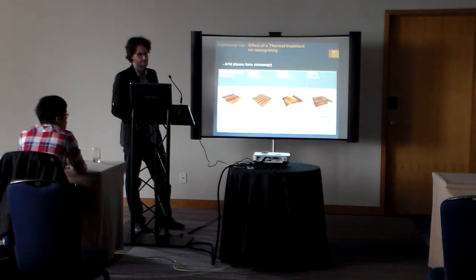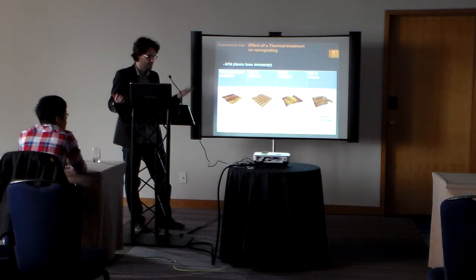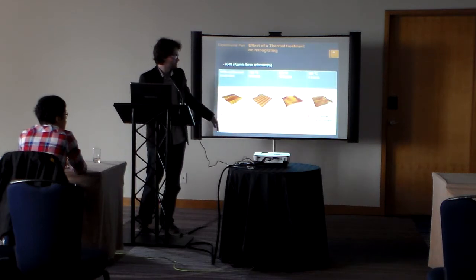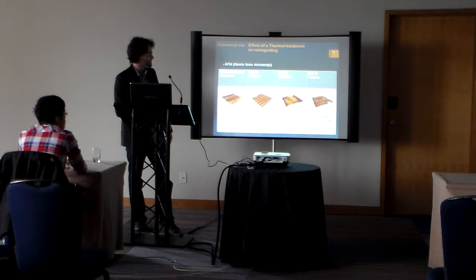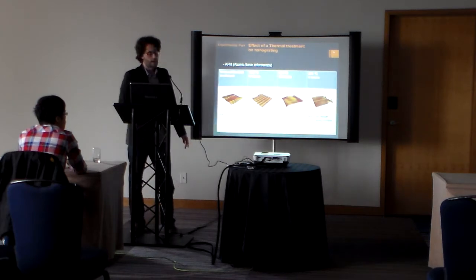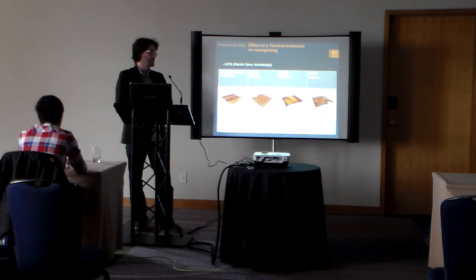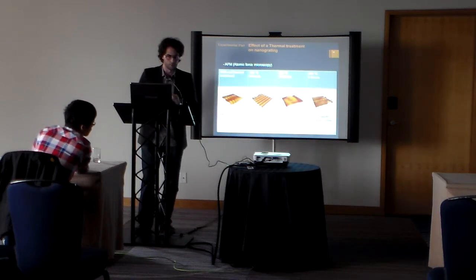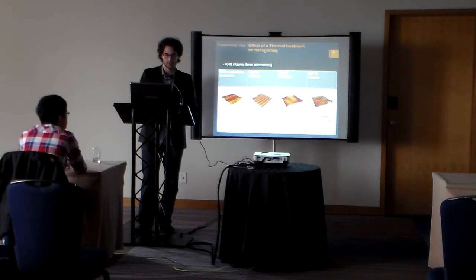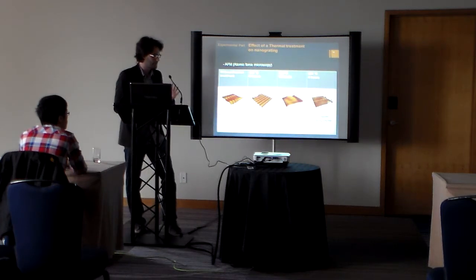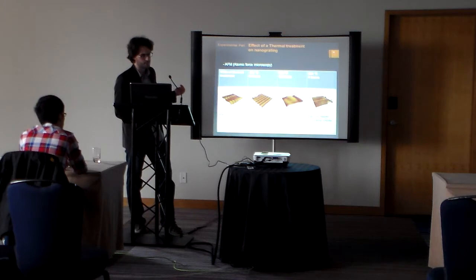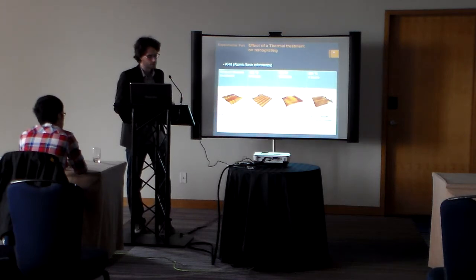First of all, the 1-hour treatment didn't change anything on the structure, well, anything visible. The 6-hour treatment really decreased the height of the structure to 23 nanometers. And at 10 hours, we obtained 17 nanometers. But at 200 degrees for 4 hours, the gratings were completely erased. But it was really a short period for our thermal treatment. So we decided that thermal treatment was more efficient and at a good pace at 180 degrees. It would less affect the overall structure of our glass.